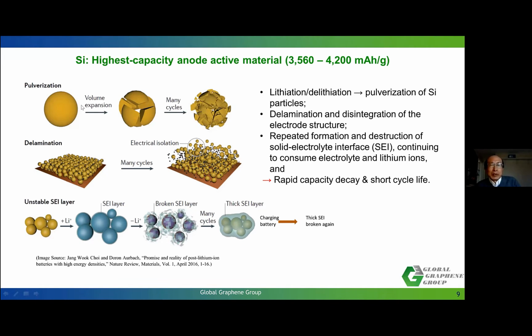So when you charge your battery, lithium ions get diffused into your silicon particle, for example. Upon repeated expansion and shrinkage of the silicon particle, the particle becomes pulverized into many pieces, and that creates some very severe problems. In other words, those pieces will lose contact with your conducting network.